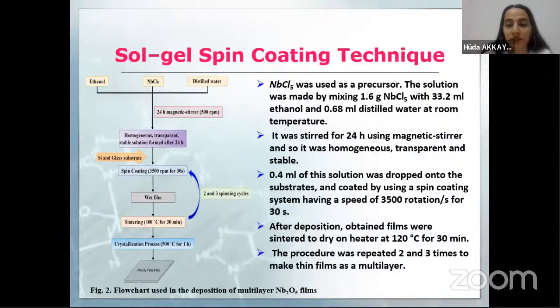The solution was made by mixing 1.6 gram niobium pentachloride with 33.2 milliliter ethanol and 0.68 distilled water at room temperature, and then it was stirred for 24 hours using a magnetic stirrer. Then 0.4 milliliter of this solution was dropped onto the silicon and soda lime substrates, and then coated using a spin coating system at a speed of 3,500 rotations per minute for 30 seconds. Why 3,500? Because the most homogeneous films are produced at a spinning rate of 3,500 RPM. After deposition, we dried it on a heater at 120 degrees for 30 minutes, and then the procedure was repeated 2 and 3 times.